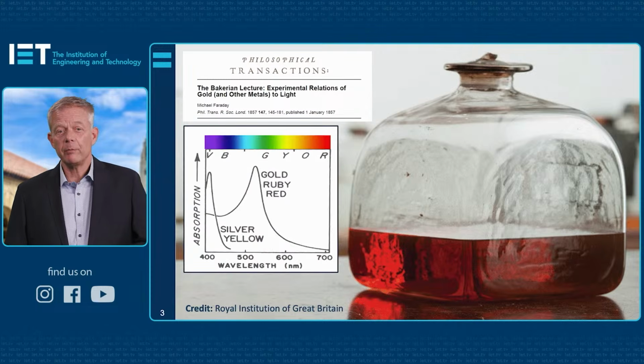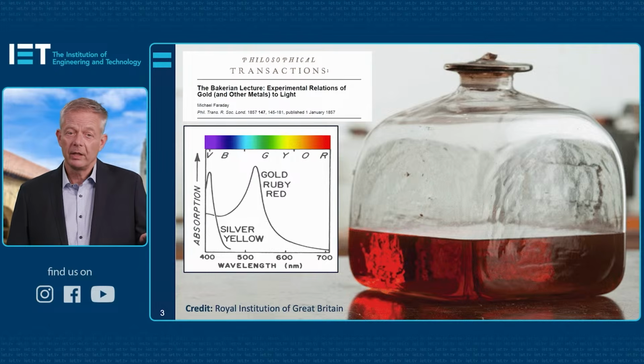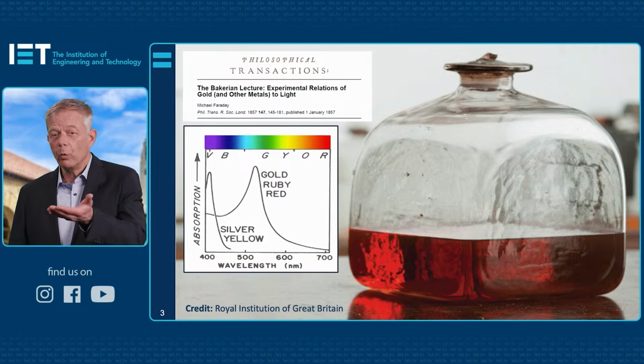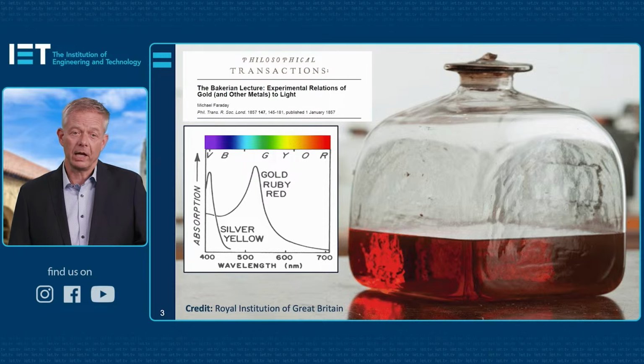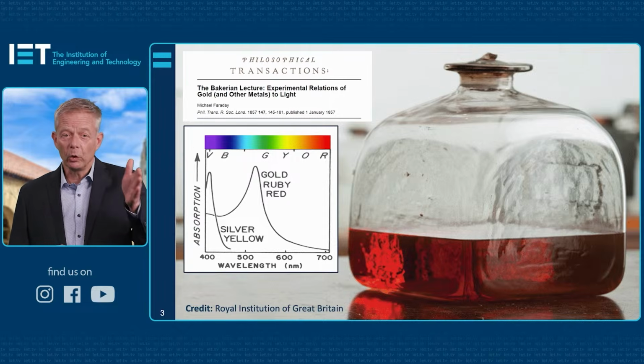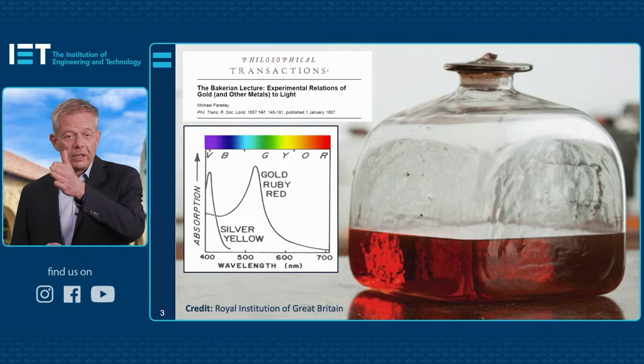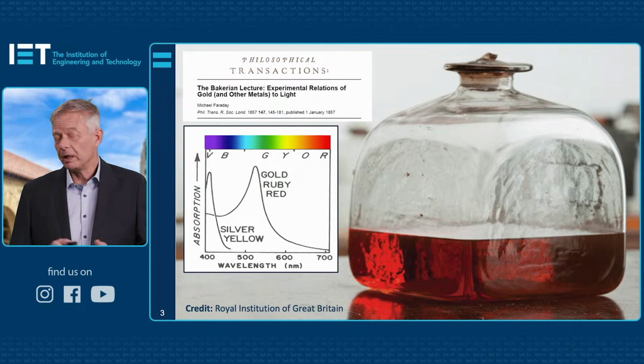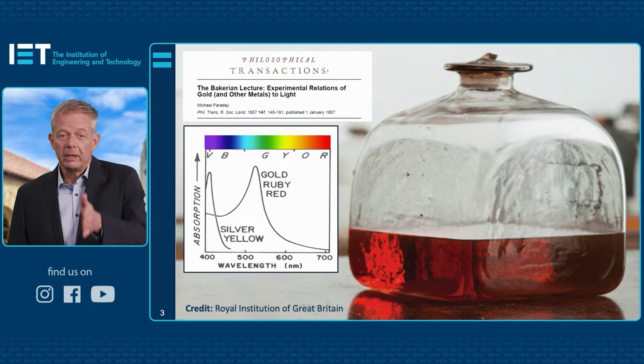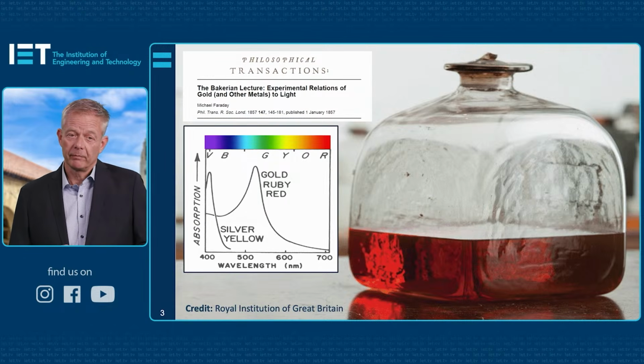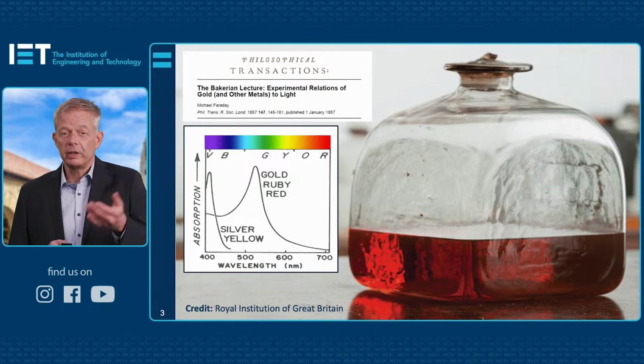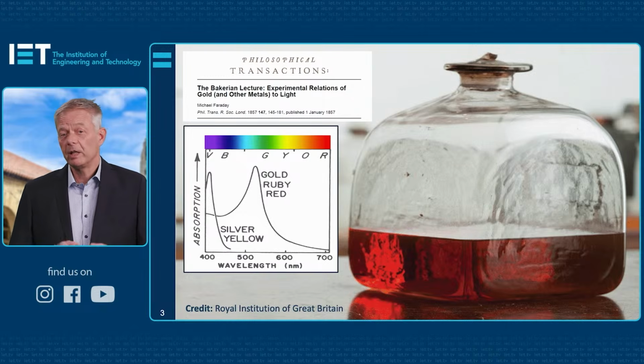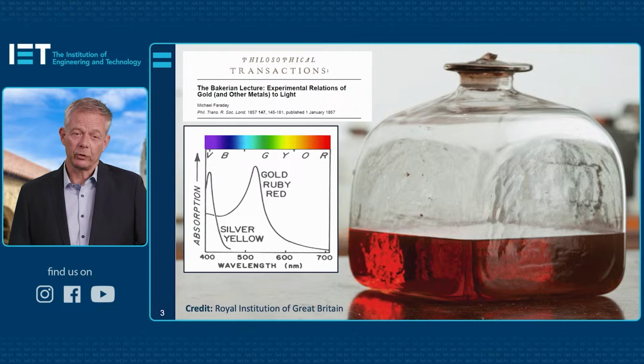If you take a light absorption spectrum, as shown on the left, where we plot the absorption versus the wavelength of light, which represents the color, the spectrum goes all the way from the violet to the greens, all the way to the red. You'll see that the absorption of this vial of gold nanoparticles made by Faraday shows a peaked absorption somewhere in the blue-green part of the spectrum. And because the purples, the blues, and the greens are strongly absorbed, the red light tends to be transmitted, giving this vial such a beautiful red ruby color.